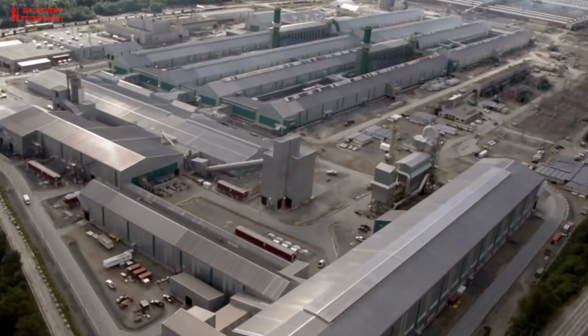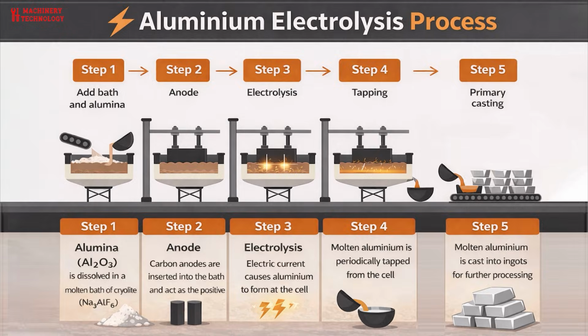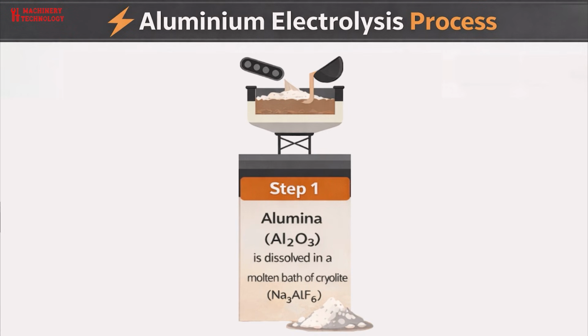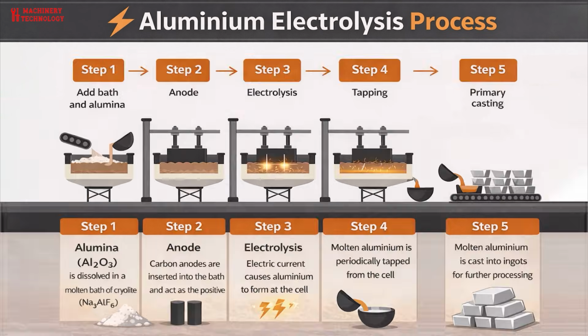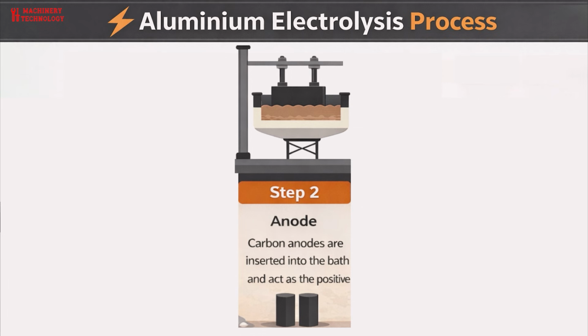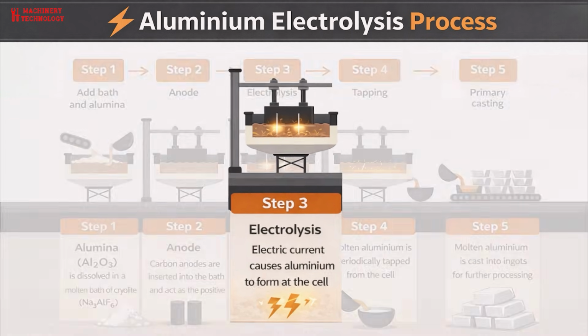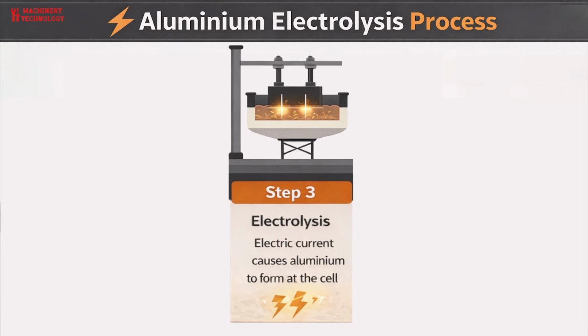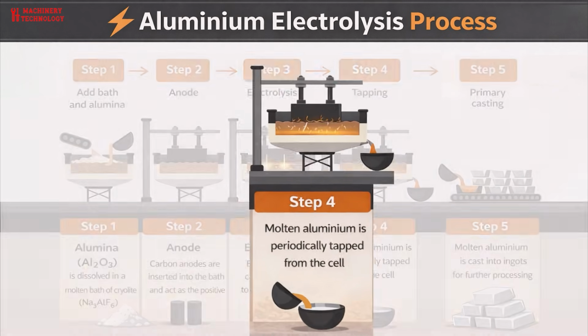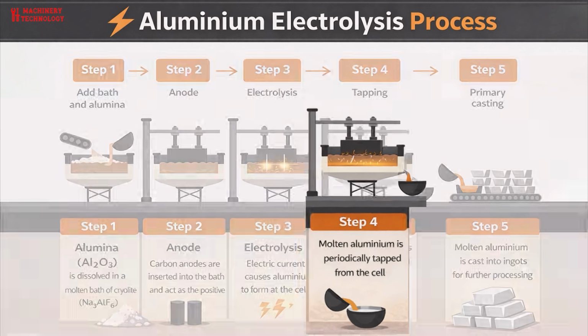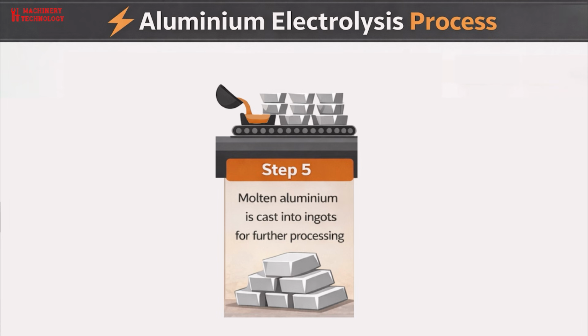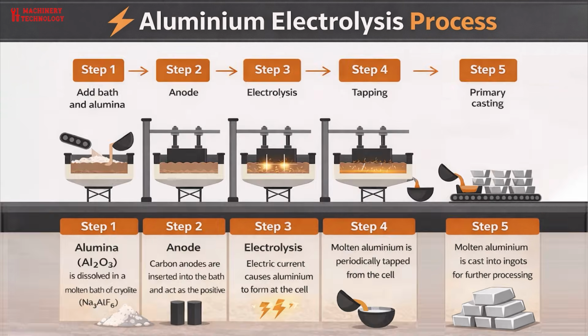At the heart of aluminium production lies a controlled electrochemical process. First, alumina, aluminum oxide, is dissolved into a molten cryolite bath, creating the chemical conditions required for electrolysis to take place. Next, carbon anodes are lowered into the bath, forming the positive electrodes of the system. When a powerful electric current flows, electrolysis begins. Aluminum metal is released and slowly settles at the bottom of the cell. Periodically, the molten aluminum is tapped from the cell. Finally, it is cast into solid ingots, marking the completion of aluminum smelting inside the plant.